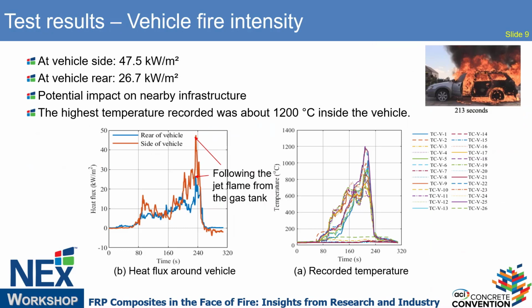So this is what we measured during the vehicle fire test, and the left plot shows the heat flux we have measured. The maximum heat flux at the vehicle side is 47.5 kilowatts per square meter, which is relatively high. The other heat flux sensor at the back side of the vehicle measured 26.7 kilowatts per square meter. So imagine if this happens on a cable bridge, right?